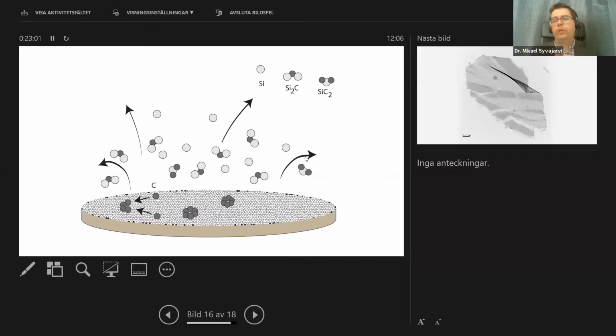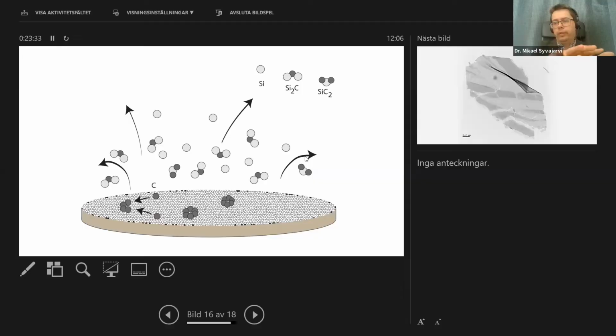I can also give another example where the mechanical properties become the most crucial thing. We also work with graphene on silicon carbide. So when we have the silicon carbide and when we heat it up, we have silicon and carbon. And when there's more silicon lost, then we have a carbon layer on top, and that is graphene on silicon carbide. So that's how we came into the graphene on silicon carbide many years ago. And before that, when we were growing silicon carbide and when we failed ultimately, then we graphitized the surface by this process. And now we have been controlling it for 15 years to have one layer of carbon. But that's how we came into the graphene.